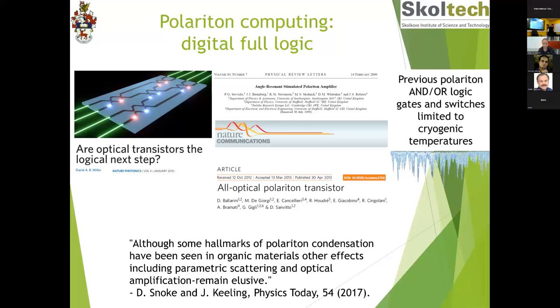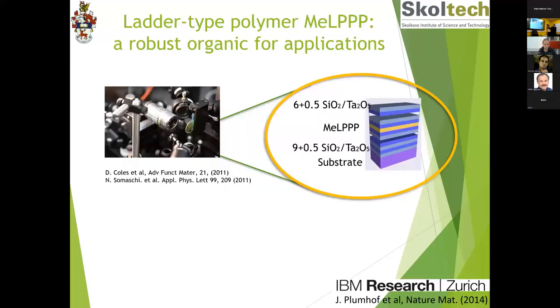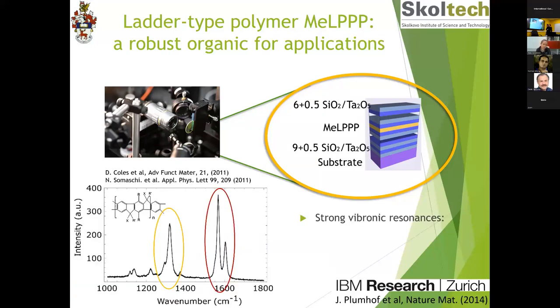And that was quite some challenge for us because we had just started the work with IBM. So we set out to work with this magic sample, this little yellow glass that you see here, where inside the microcavity there is an oligopolymer, a ladder-type polymer, which is called MeLPPP. And this material carries excitons, optical transitions, which are resonant to the cavity, but at the same time it has very strong vibrational modes, the equivalent of phonons in inorganic semiconductors. Because it is a very stiff ladder-type polymer, the vibrational modes carry a lot of energy.